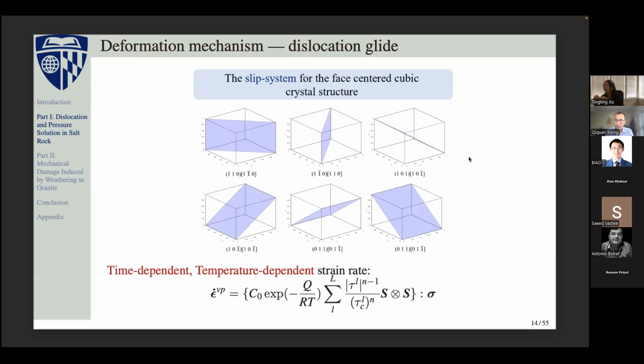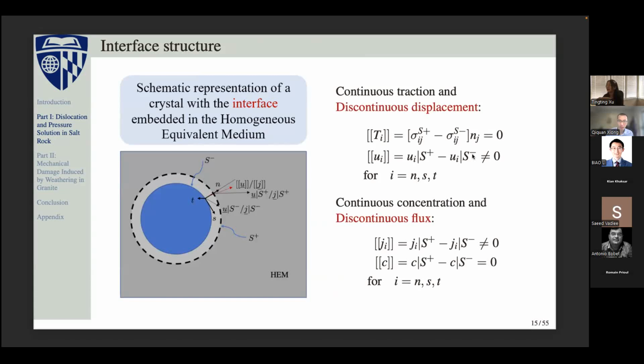And as I just said, the first deformation mechanism that we want to consider is dislocation. Here is a sketch of the slip system of this face-centered cubic crystal structure. From this sketch, we can get the time-dependent and temperature-dependent strain rate relation as the equation shown here. This is a viscoplastic strain rate, and it's dependent on the temperature and also on the stress applied on this single crystal.